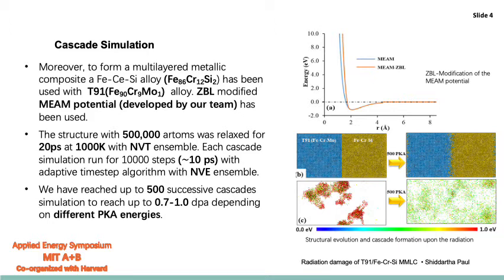Here the DPA is the displacement per atom, which is a measuring factor for the radiation dose. For reaching that particular DPA level, we had to introduce around 500 primary knock-on atoms into the structure. In the figure we can see how the sharp T91 iron chromium silicon interface gets thicker upon the introduction of the radiation dose. We can also see the energy cascade formation behavior upon the increment of the radiation dose for this particular T91 and iron chromium silicon MMLC.